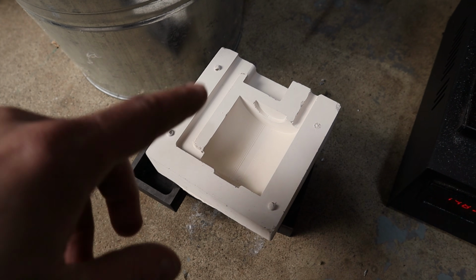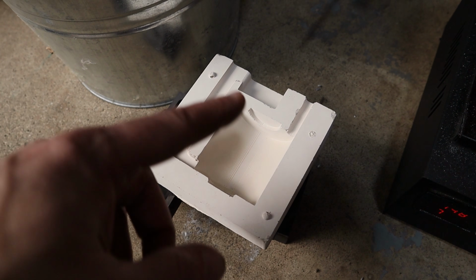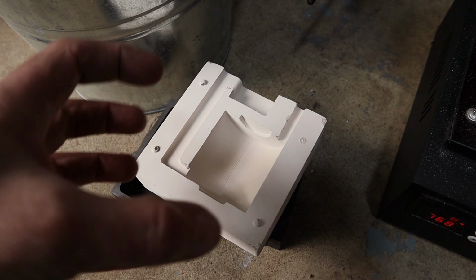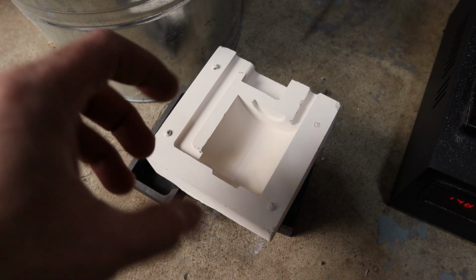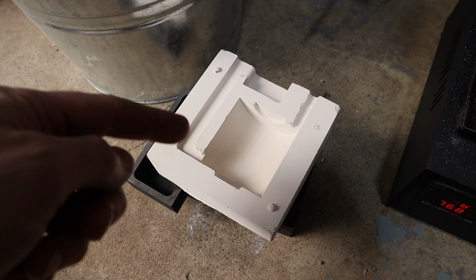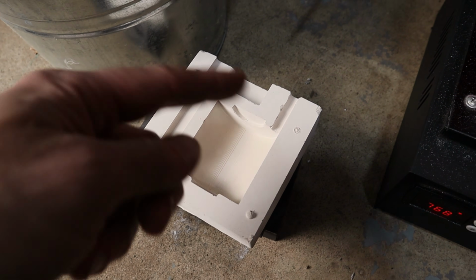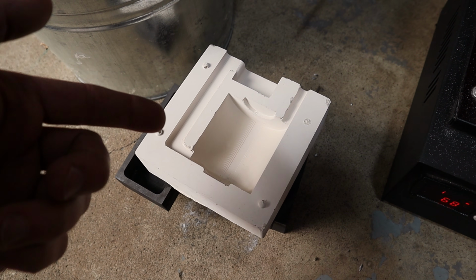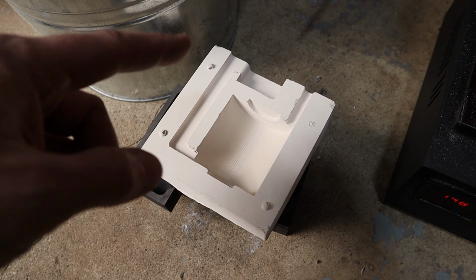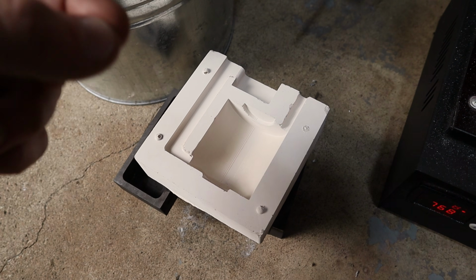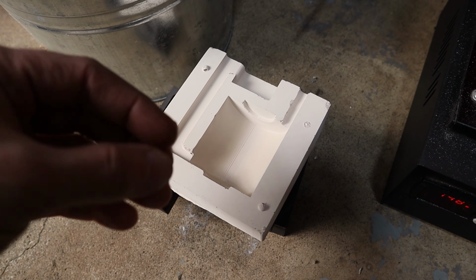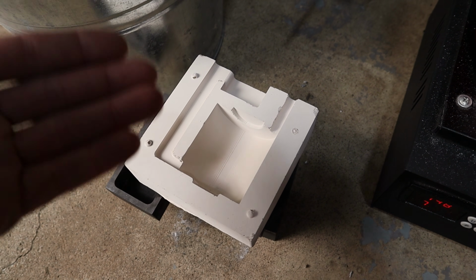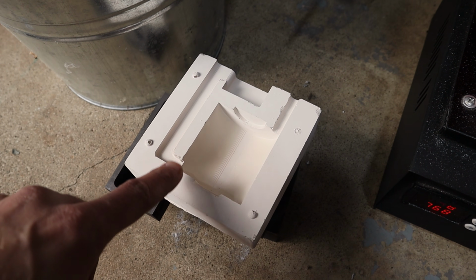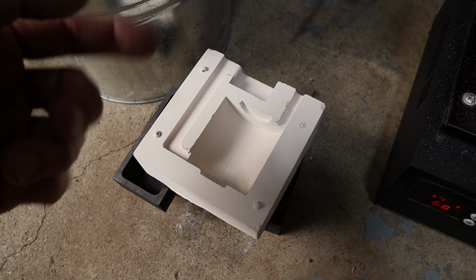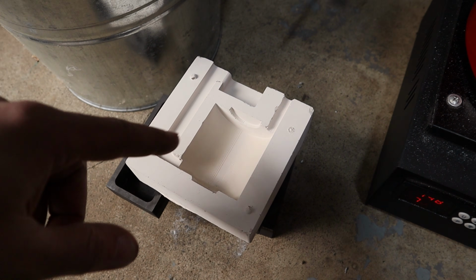So in your typical Lost PLA setup, you will have a plaster mold, but it's going to completely encase the PLA part. And what's going to have to happen is you need a burnout process to get rid of all that PLA in there, just like you would if it were a wax mold. So in this process though, we've done it completely differently. We have it so that you can separate it into two pieces. You get the PLA out of there, and then all you need to do is dry this. So it becomes a lot easier. You don't need another furnace.